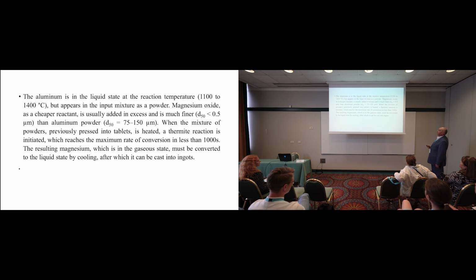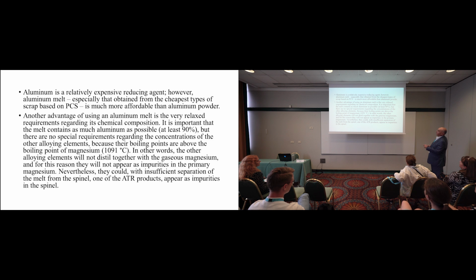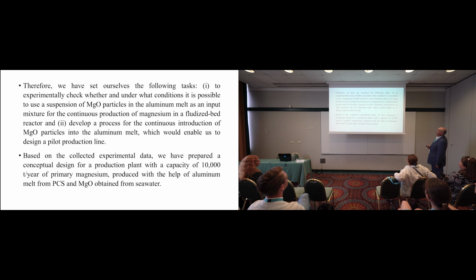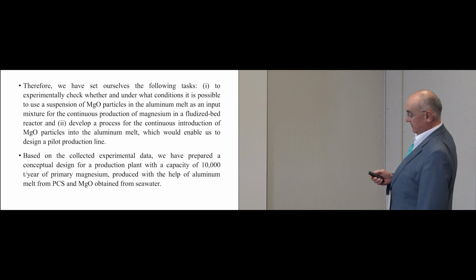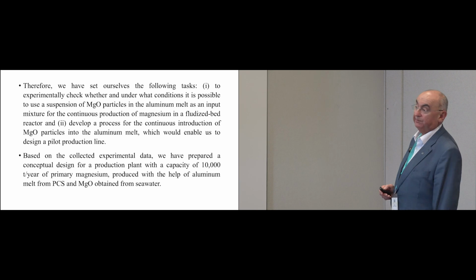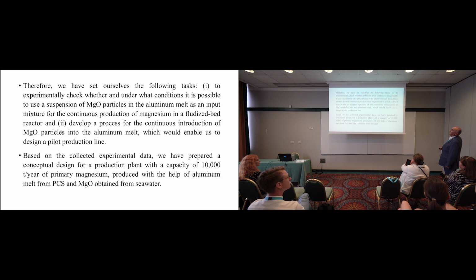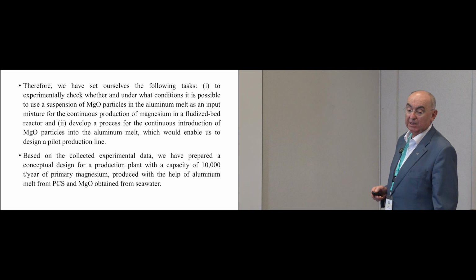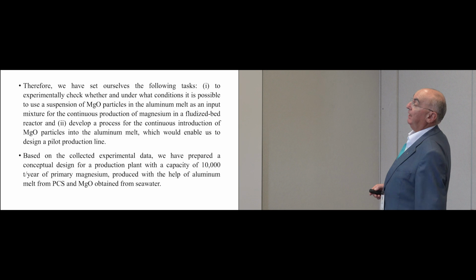So we try to investigate here, it's a lot of information, but what we try to investigate is under what conditions it is possible to use a suspension of magnesium oxide particles in aluminum melt, because this could be the cheapest way, as an input mixture for continuous production. When you are mixing two powders and pressing the pellets, you are working in a non-continuous way. You just put it in the furnace and make the aluminothermic reduction, and then you repeat the entire process.